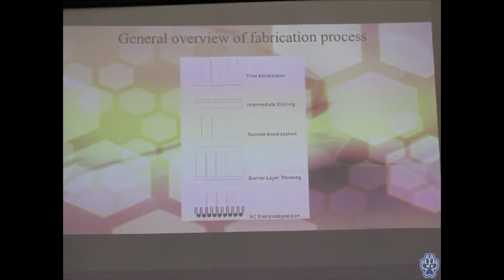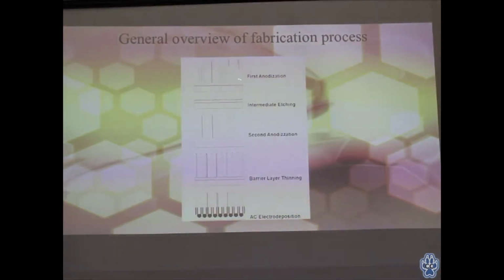You're going to do an anodization process, which usually after the first anodization you will have these pores, but they're not very symmetric and they're not very highly ordered. So what we want to do after that is you want to do an intermediate etching with a very strong acid, which will dissolve the oxide and leave basically this like mask, we call it, on top of the aluminum, which then allows us to perform further anodizations, which increases the order and the symmetry of these pores because now they are pretty symmetric and they stand upright.